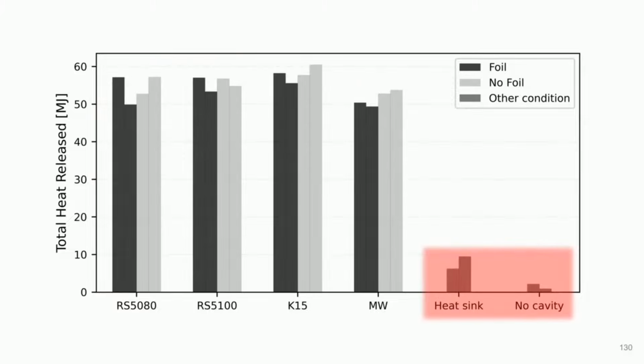Finally, in cases where there was no escalation, i.e. where the cavity was not insulated at all, or there was no cavity at all, the total heat released was very small, albeit there does appear to be a small influence from the presence of the cavity. The experiments that had cavities, if you watch the videos, you'll see that the pool fire is larger and burns for longer in those cases, hence a slightly higher heat release.